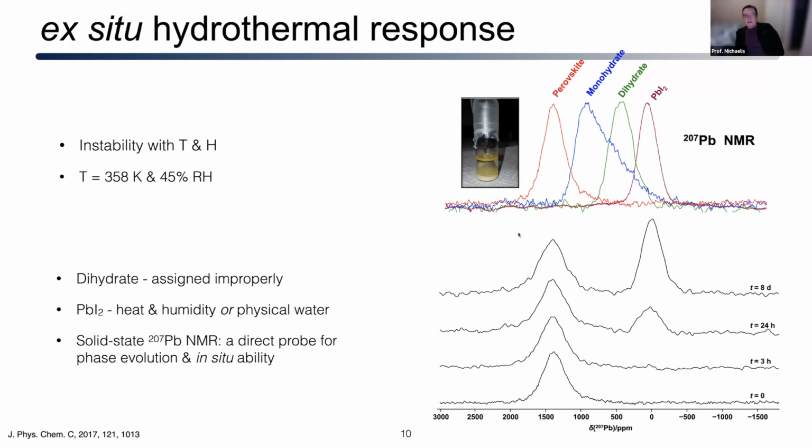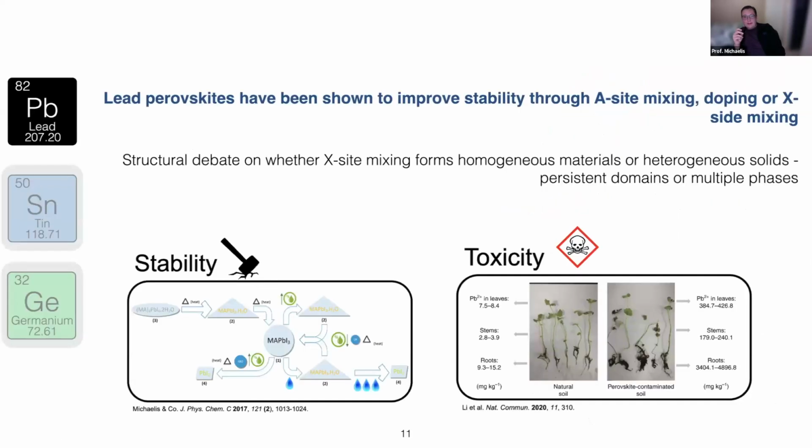And what ends up happening here is the methyl ammonium molecule itself is dynamic and it's fairly labile. As you heat it, it basically allows it time to leave the actual crystal structure. And then you basically degrade it to excess iodine and some residual lead iodide, okay? And so this got us to thinking, how can we look at ways to stabilize this material and potentially avoid the degradation aspect of this.